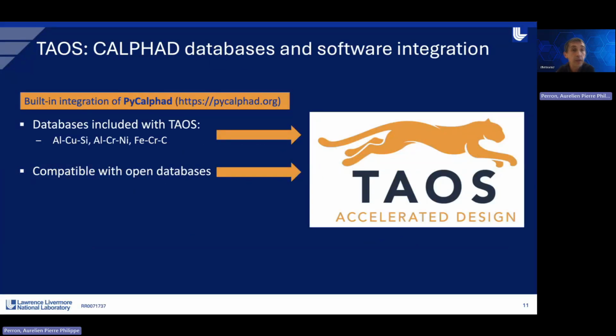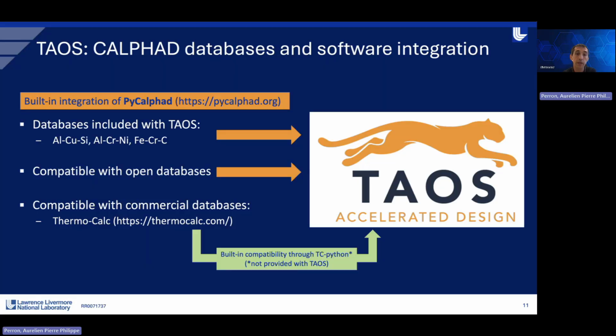So coming back to TAOS, I said that we include as a backend CALPHAD database and software. So it directly integrates PyCalphad, a thermodynamic engine to run CALPHAD calculations. And we also include some thermodynamic databases where you can run some examples and test the software. You can also have access to open databases in the literature, so TAOS is compatible with these open CALPHAD databases. And if you are interested in a third-party provider, TAOS is also compatible with the Thermo-Calc databases through the TC Python interface.